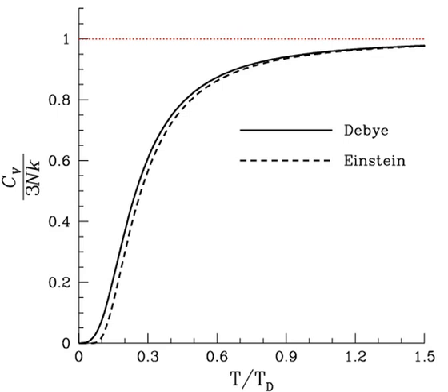In solids, the quantitative limit of heat capacity in general is about 3R per mole of atoms, where R is the ideal gas constant. This 3R value is about 24.9 J per mole-K. Six degrees of freedom, 3 kinetic and 3 potential, are available to each atom. Each of these 6 contributes 1/2 R specific heat capacity per mole of atoms.